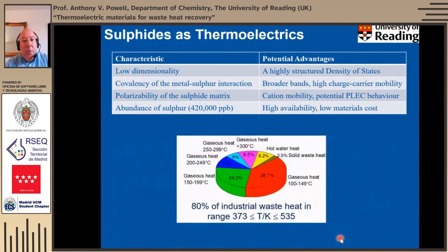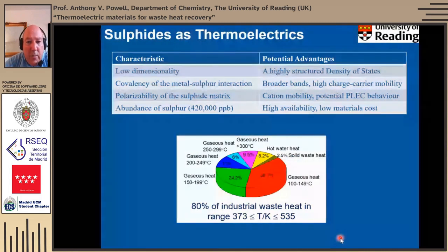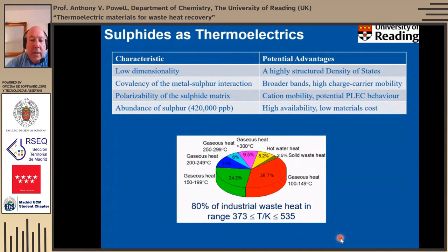And the other point that attracted us about sulfides is that because of the temperature range in which they're stable and they show high performance, they're well suited to industrial waste heat. Some estimates of industrial waste heat indicate that about 80% of it is released in this temperature range, over about 373 to 535 Kelvin. That's a very good range for sulfides because sulfides are not especially stable at higher temperatures.